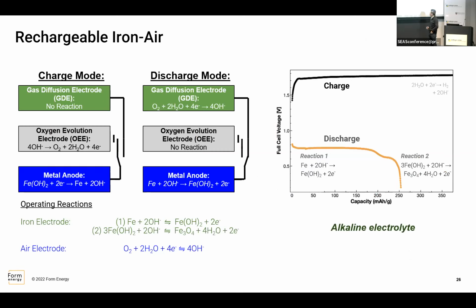A couple of the interesting requirements come into play in order to make a functional iron-air battery. If you think of the air electrode, that's like the lung of the battery, right? The iron is oxidizing, reducing, and the air electrode breathes in and exhausts oxygen, so it's a lung, right? Now, our lungs are so-called bifunctional. You both inhale and exhale. It turns out that to make an iron-air battery work, it's desirable to have two electrodes, one to inhale and one to exhale, right? So you have essentially two lungs, two oxygen electrodes. The green one is the oxygen reduction electrode that takes in the oxygen. The gray box is the oxygen evolution electrode, that's the exhale. So that's how this design works.